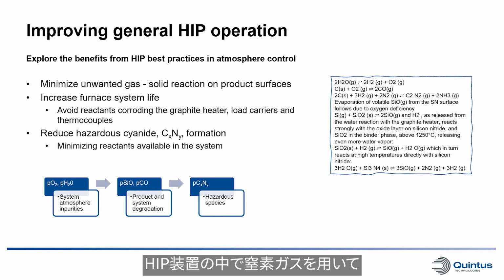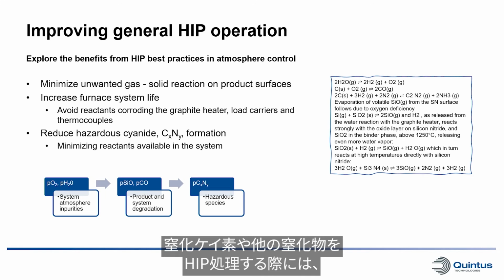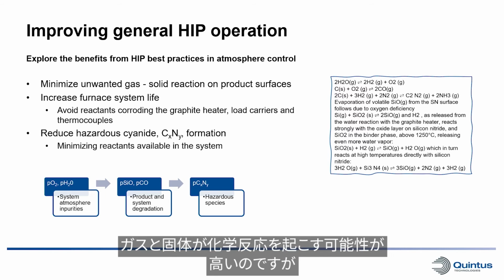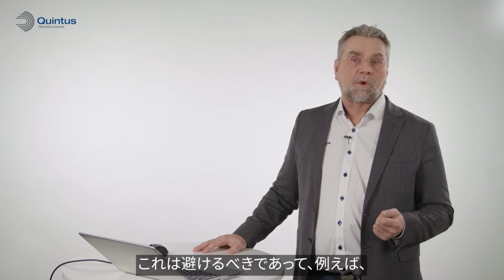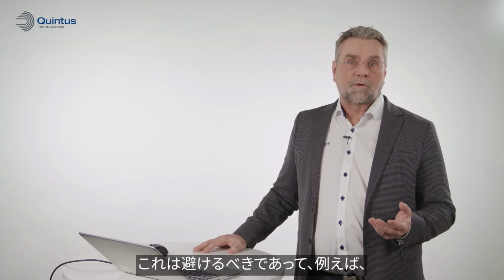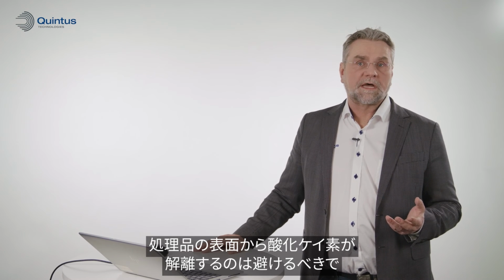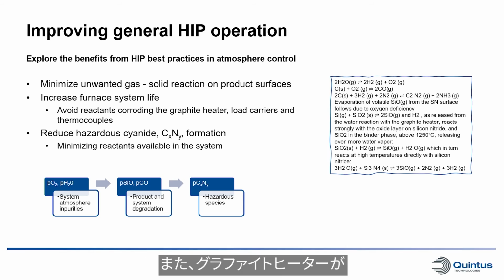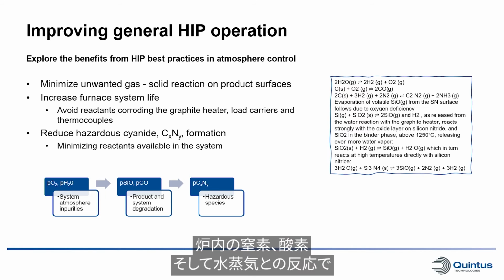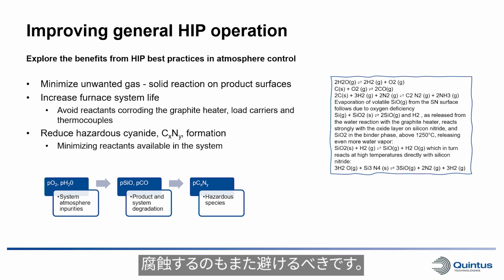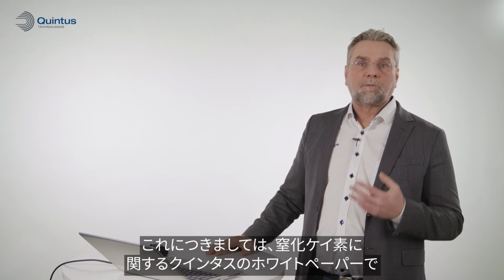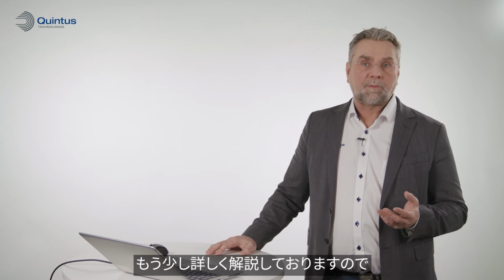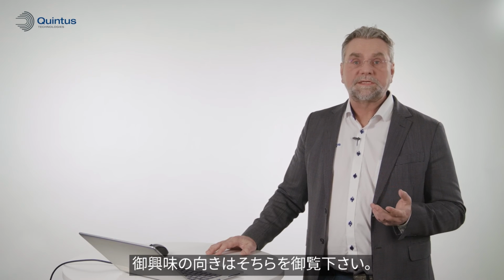When HIPping silicon nitride and also other nitrides using nitrogen gas in the HIP system, we will of course have a lot of possible chemical reaction between gas and solid that we want to avoid. One thing is, of course, that we don't want silicon oxide leaving the component surfaces. And of course, we don't want the graphite heater to corrode away from the reaction with the nitride and with oxygen and water vapor inside the system. We elaborate a bit more on this in the white paper for silicon nitride, so please look into that if you have more questions.